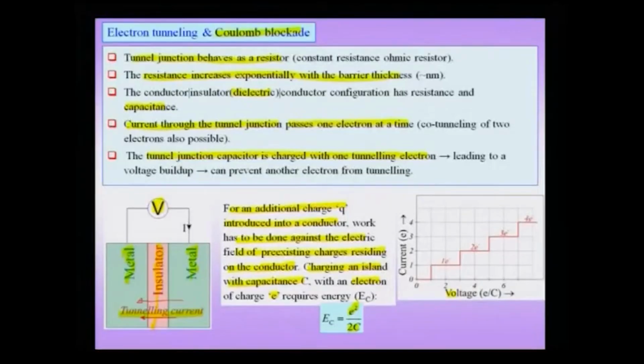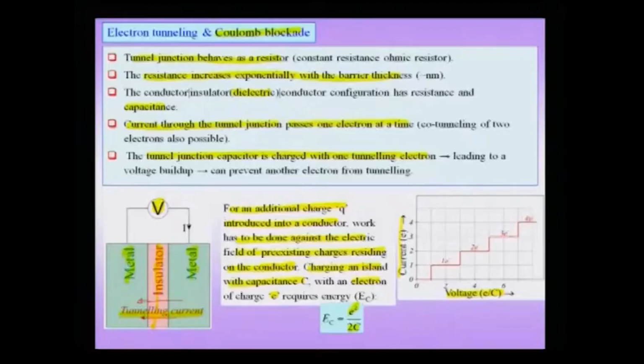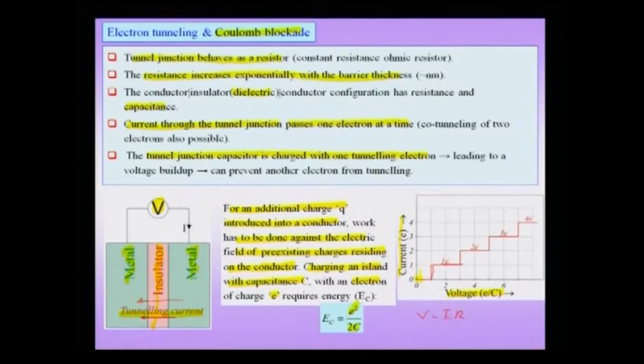If I now plot my voltage-current characteristics, this becomes very different from what we normally observe for normal materials, like a normal conductor. We know the V equals I R kind of relationship. That means the current goes linearly with voltage, but you can see that in such a system, wherein I have a metal-insulator-metal configuration, the current-voltage characteristic has a staircase kind of structure.